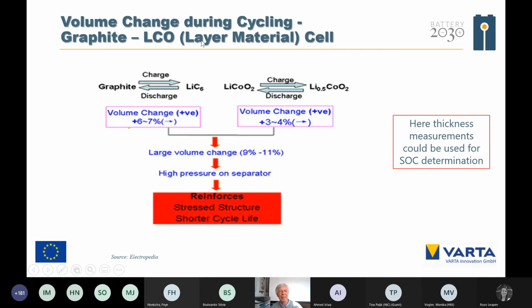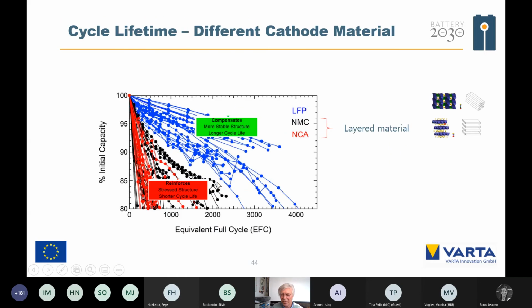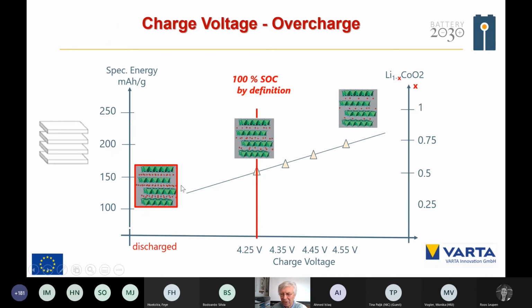In the case of the layered material, for example LCO, for the graphite 6-7%, for the LCO plus 4, and that adds up to about 10% volume change, and then you have high pressure on the separator and stressed structures. And if you look, for example, at the lifetime of LFP cells and layered material cells, you can see the advantage of the LFP, which compensates all the volume changes from the anode and the cathode, and that is not the case for the layered material.